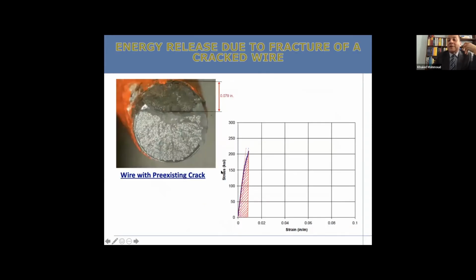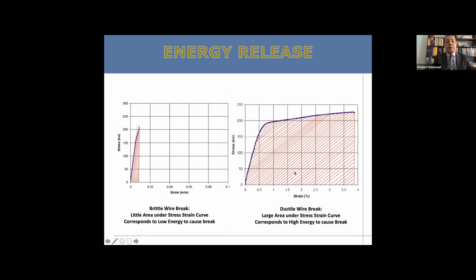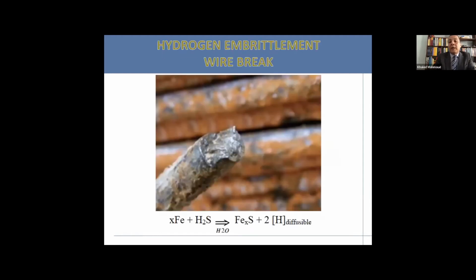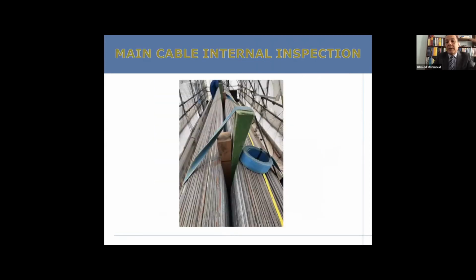And you look at the stress strain curve. Now you can appreciate what kind of damage the embrittlement induces on the wire. If you put the two curves together, you can, of course, find out how damaging the embrittlement is and how to deal with that further. Again, this comes about, you have the H2O, here's a hydrosulfide, here's the iron, and you have on the right side of the equation the diffusible atomic hydrogen that causes the embrittlement and causes the furthering of the crack growth up until the break takes place.